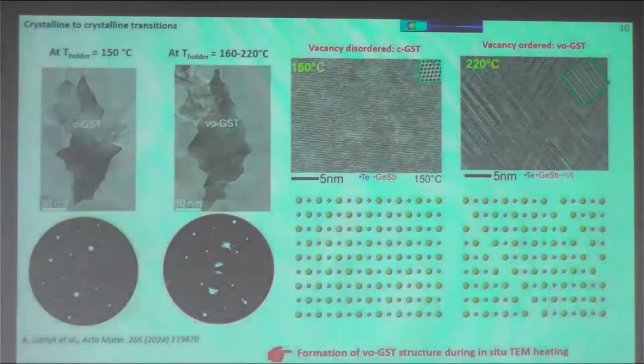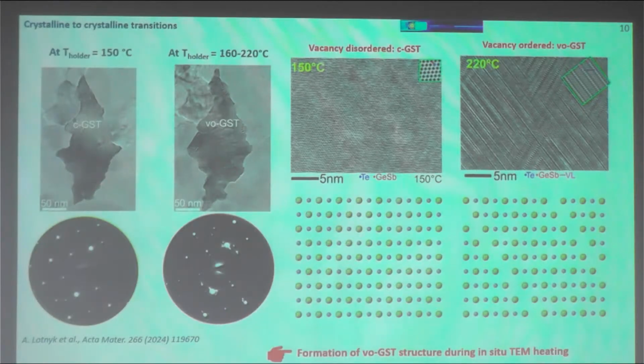So now let me consider some crystalline phase changes. Such crystalline to crystalline phase changes can be nicely studied by in situ or ex situ methods. In this case, we performed in situ electron microscopy, and we were interested in this crystalline to crystalline transition, particularly in the cubic GST phase. So what happens if we find such a large grain in our thin film, and then if we heat up, what happens if we can observe other phases, like in an in situ TEM.